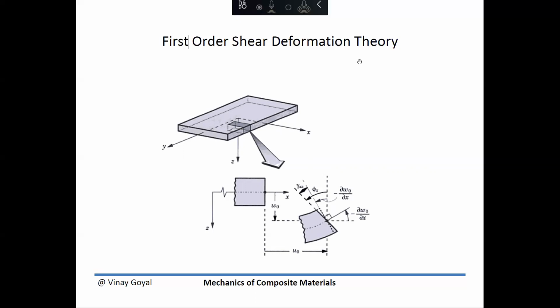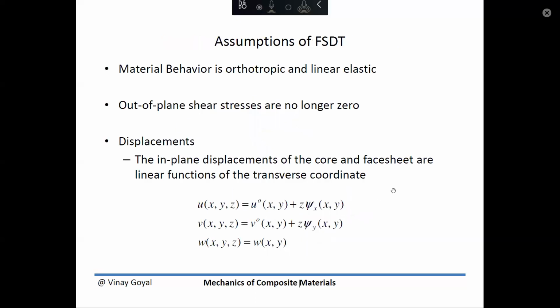This first order shear deformation theory was developed by Reissner and Mindlin for isotropic materials. The total deformation of the system as you bend the plate is given by this shear, but also the slope of the mid-surface can be accounted for. The assumptions in this theory are that the material behavior is orthotropic and linear elastic. And in this case, the out-of-plane shear stresses are no longer zero. The displacement assumptions now, in that case, are given by these deflection assumptions.